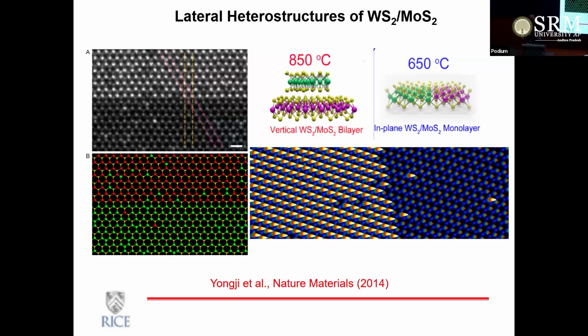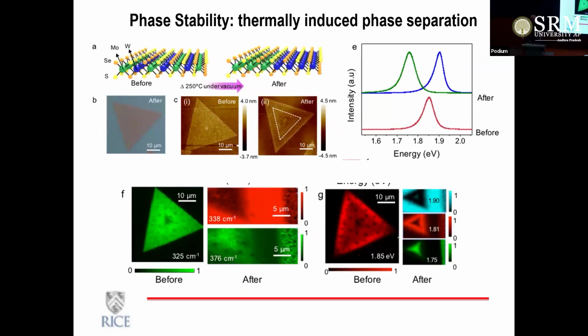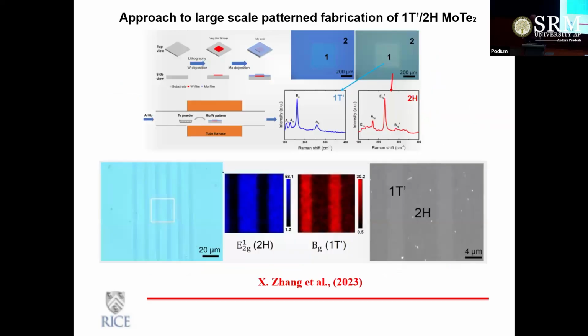In fact, the stability of these type of structures are fascinating from a materials point of view. In fact, we have done many experiments to see how the structures go from unstable to stable states. So, for example, if you have these lateral junctions, you can heat it and they could actually start to mix at some point in temperature. And you can actually monitor this in situ in a TEM to see how the atoms are actually moving around and how the atoms can be controlled. So again, this is the kind of thing that is important to be able to create these heterostructures, and also to control the mobility of atoms, to understand the mobility of atoms in these type of systems.